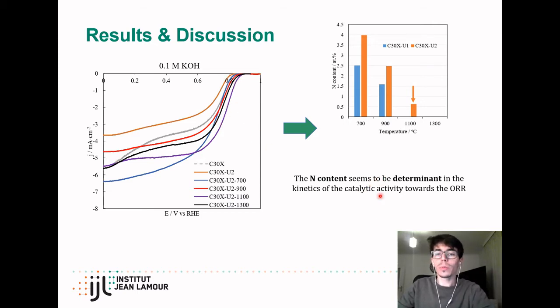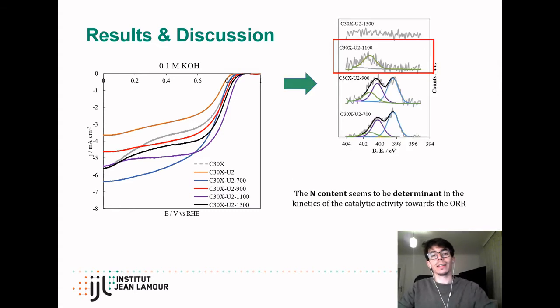So the nitrogen content seems to be determinant in the kinetics of the catalytic activity towards the oxygen reduction reaction, but the other very important point is the type of nitrogen species that we have in our material. And interestingly, the sample that showed the best catalytic performance towards the oxygen reduction reaction was the one that only saw graphitic nitrogen functional groups in its surface chemistry, supporting and confirming the key role of the graphitic nitrogen functional groups in the catalysis of the oxygen reduction reaction.